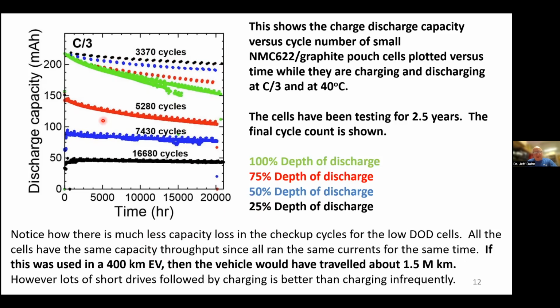All these cells are undergoing the same amount of charge throughput. They all would have driven a vehicle the same distance, about 1.5 million kilometers. But at the end of this time, the battery that operated over the 25% depth of discharge has lost far less capacity than the battery that's operating over 100% depth of discharge. So what this means is lots of short drives followed by charging is better than charging infrequently.